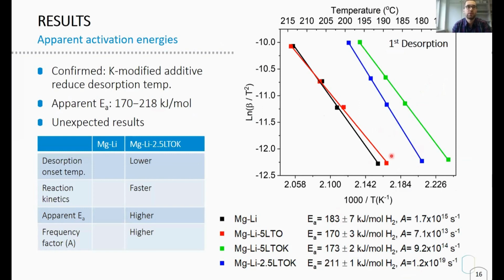At this point, we have unexpected results, since samples containing potassium have lower onset temperatures and faster reaction kinetics, but these samples have higher apparent activation energies and a higher frequency factor, which is related to collisions between amide hydride particles. In order to shed light on this fact, I calculated the kinetic constant by the Arrhenius expression.